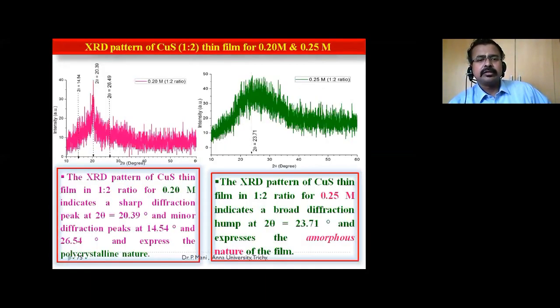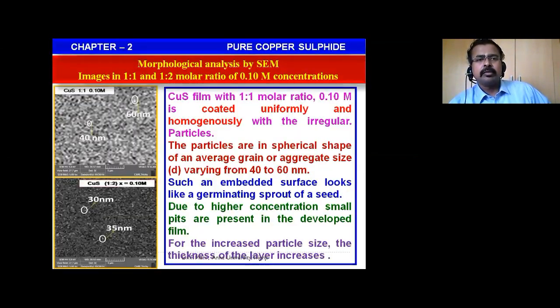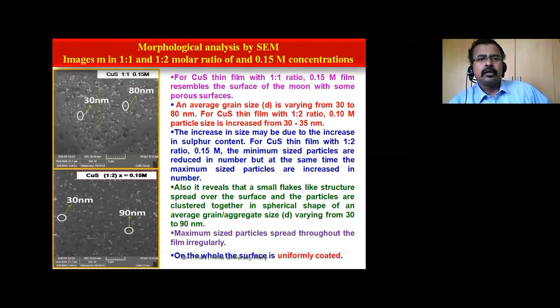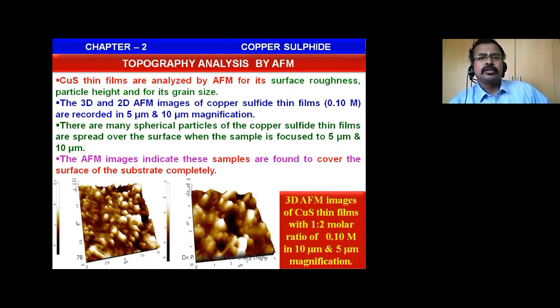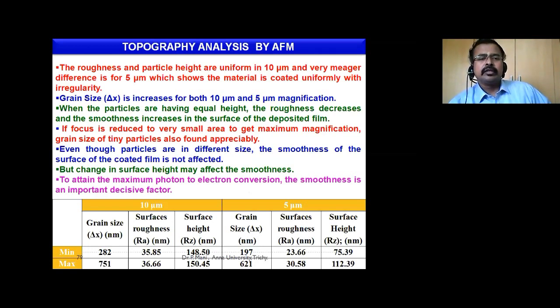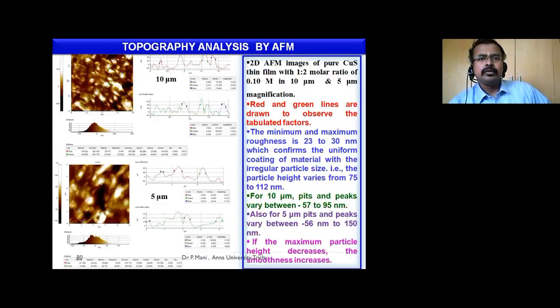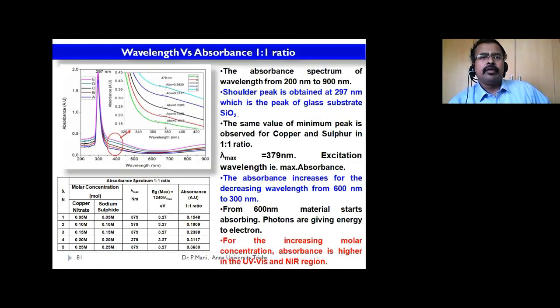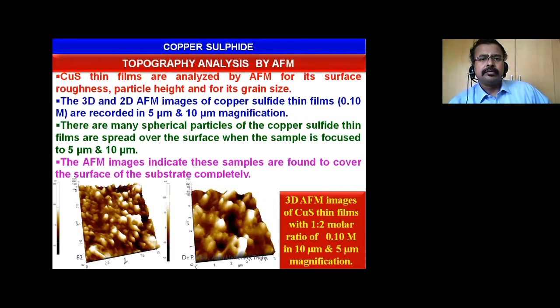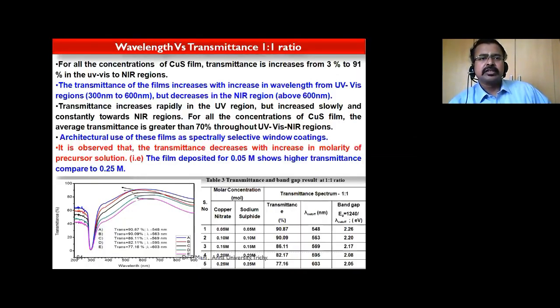We are seeing the calculations. And here, the first one is polycrystalline, and the next one is amorphous. And we are seeing the same result. Here, the film is coated uniformly and homogeneously. And we are seeing topography analysis. Here we are getting the results as grain size, surface roughness, surface height for 5 and 10 micrometers. And wavelength versus absorption. Transmittance curve.